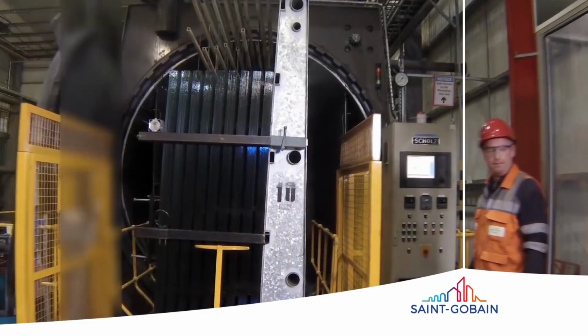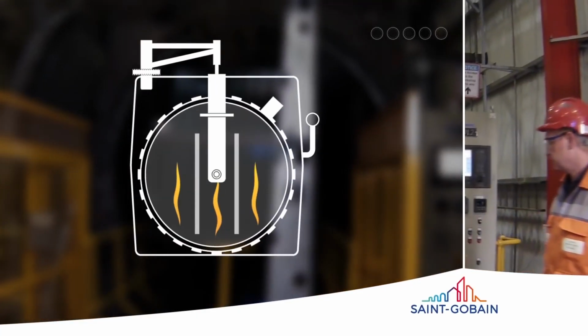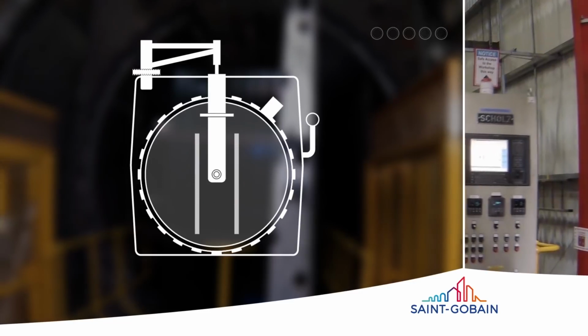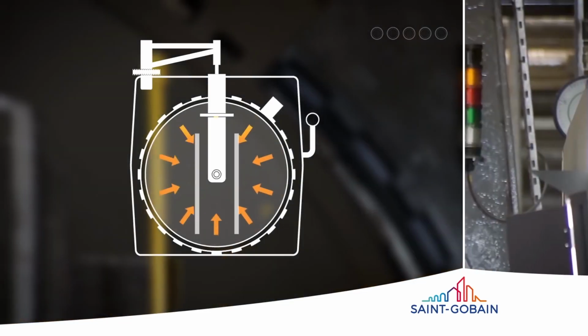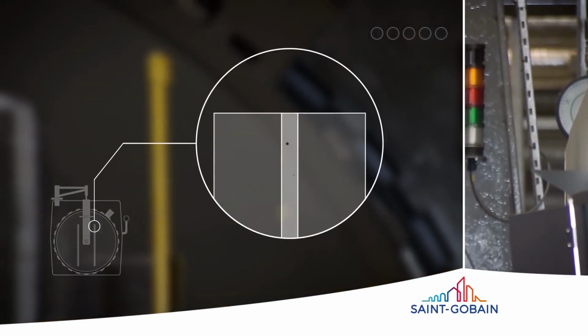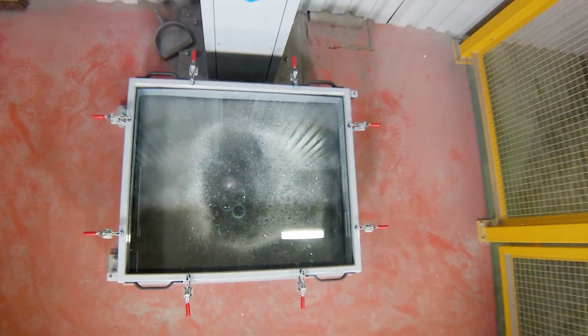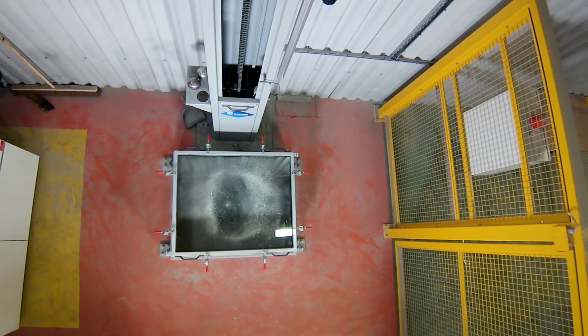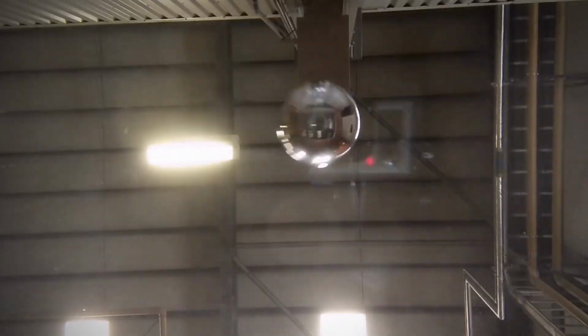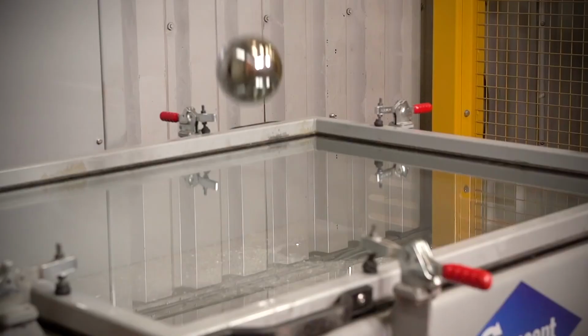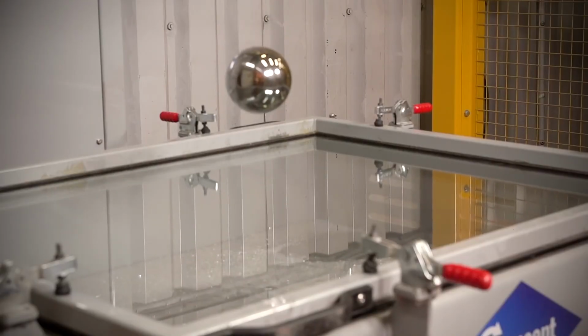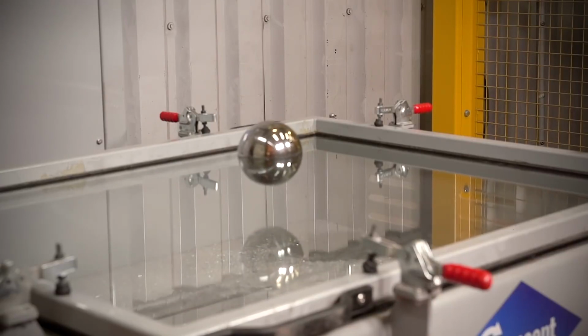The glass is now heated in an oven at up to 250 degrees Celsius to bond the PVB to the glass. Over several hours, the laminate is heated and cooled in a pressurized environment. This is the final stage of the bonding process, removing any remaining air bubbles. The result: laminated glass is strong enough to withstand the impact of a 4 kilogram steel ball dropped from 3 meters, the P2A standard.